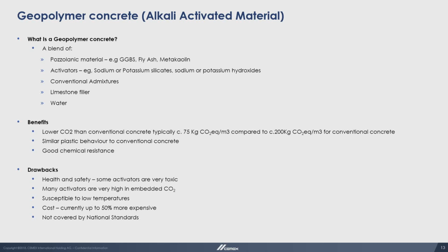Typically, they're manufactured with slag or fly ash, metakaolin, which is a kind of activated clay, or combinations of those materials, and they're activated chemically, usually with sodium or potassium silicates or hydroxides. They can be used in conjunction with conventional admixtures to control the properties of the material. Often they contain limestone fillers as well, and obviously water to get the whole reaction going.